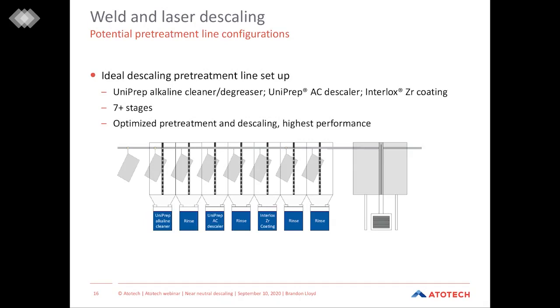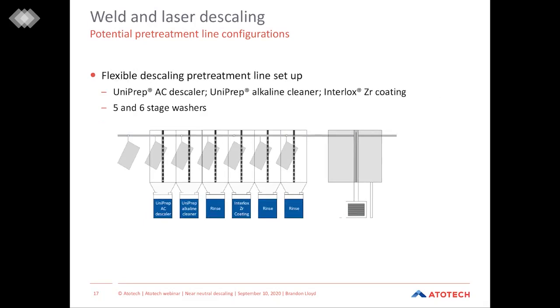So you can see in the line diagram in the bottom of this page, first we start with the Uniprep alkaline cleaning prior to rinsing. Then we would move to the Uniprep AC descaler, rinsing, the Interlox conversion coating, and then 2 more stages of rinsing prior to going to dry off and paint application. However, there's other ways of achieving this as well.